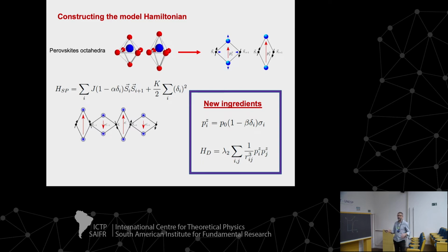So P_z is the z component of the electric polarization. You can have a sign here that can point up or down, so this is an Ising variable. Delta is the deformation, and this is some constant, and this is some fixed value. So this is the case of already present electric polarization that gets larger or smaller depending on how the octahedron deforms, okay? Also, we will include a dipolar interaction that turned out to be very important.